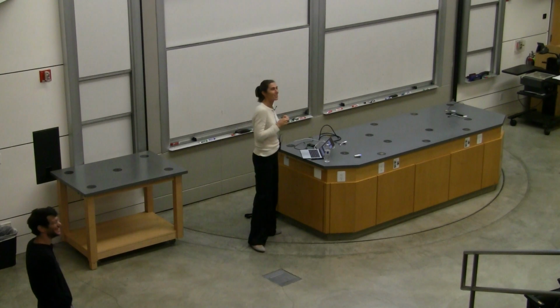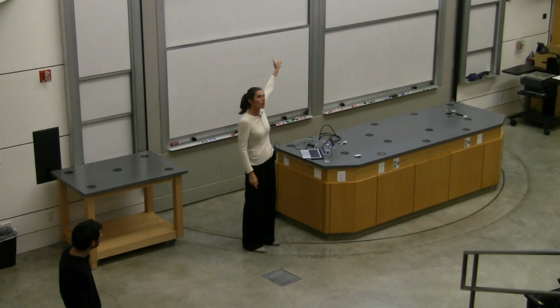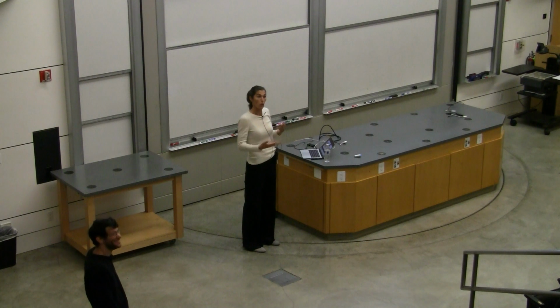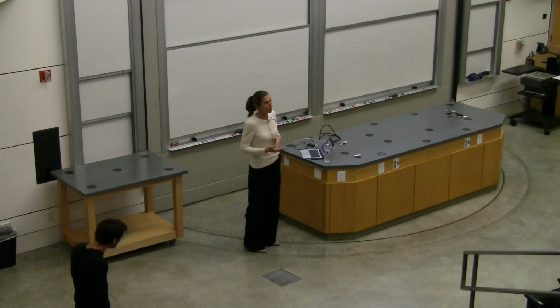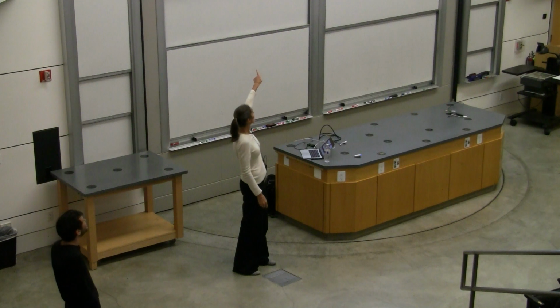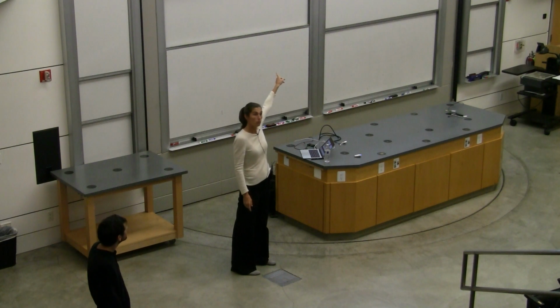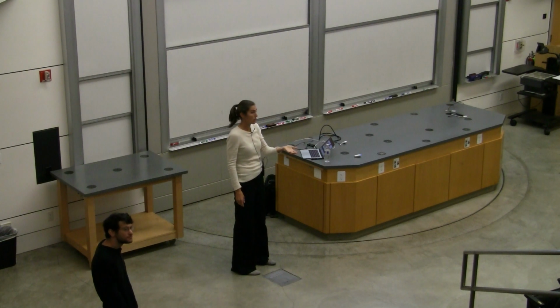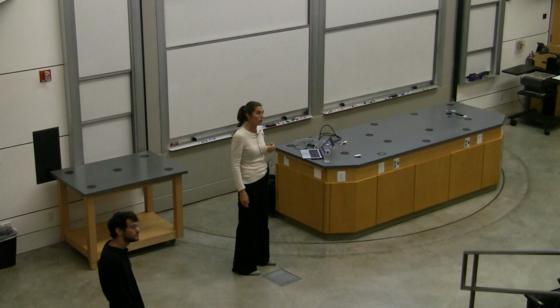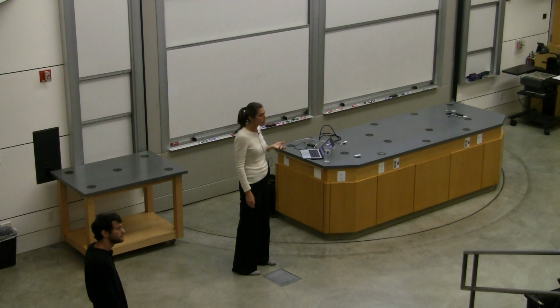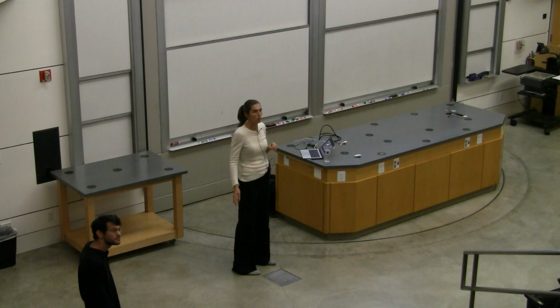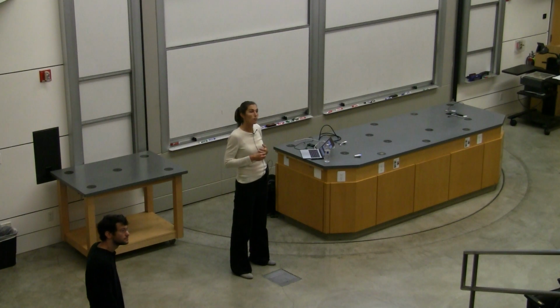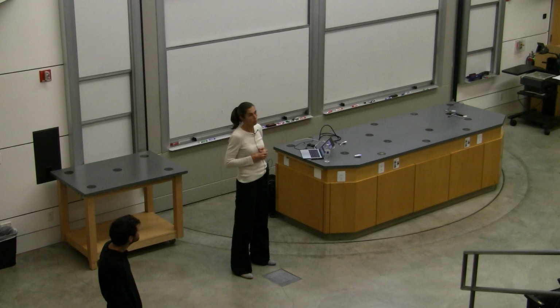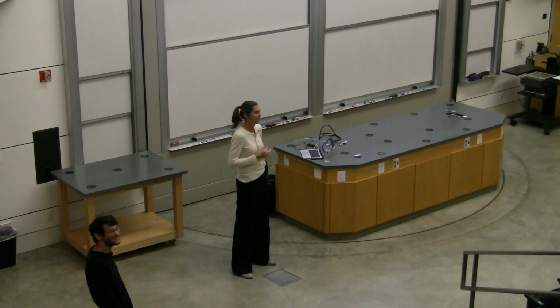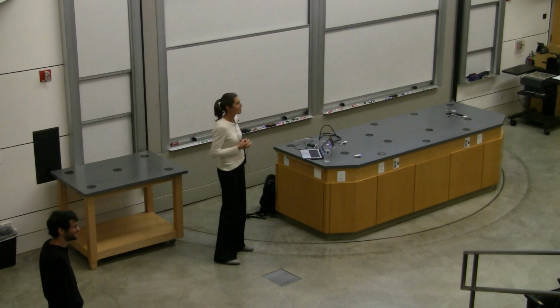No, so these types of scans, T1 imaging is particularly tedious because T1s are quite long. Since then we've also come up with other ways to make that faster, but just to give an example, this type of scan took on the order of several hours. Using some of these techniques that I've just discussed, and even some that we've already employed in our lab since this result, I think realistically one can get these types of images down to, say, tens of minutes probably. Maybe I'll just stop there. I can speculate about what one could do.